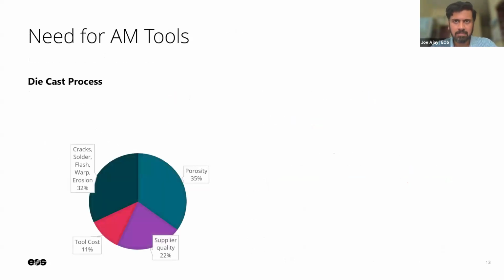So the need for AM tools, coming to the theme of the day, tools, right? So for die casting, this is an interesting survey done by NADCA, the North American Die Casting Association. They say the problems faced by die casters, the number one problem is porosity. Gas porosity, shrinkage porosity, blisters, and whatnot. Everything put together contributes about 35% of their product defects, followed by all other issues, cracks, solder on the tool, flash, erosion of the tool, right? And then you have supply quality coming in, the dimensions, CPK values, and so forth. And then finally, the least amount of headache is on tool cost, right?